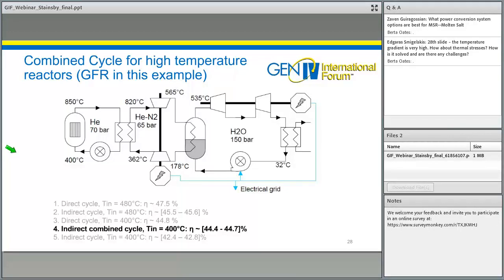In all high temperature reactors, you keep the core outlet gas away from metallic structures. So the core outlet gas will be handled completely by ceramic lined structures, either graphite lined structures in the case of VHTR, or some other ceramic insulated structures within GFR. There is nowhere in GFR, other than in things like heat exchangers and turbines, that exposes metallic structures to 850 degrees C. Again, I hope that answers the question.